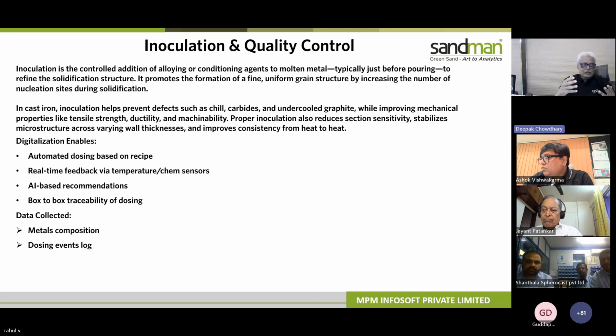I just wanted to draw my thought process with you, Mr. Gadappa. If you have a digital interface like what Rahul showed you, which also has a lot of other data capturing capabilities, and you have all the data on the scrap that you used, all the temperatures that you have used for a particular type of castings, you will be able to do a clear cut root cause analysis of what scrap combination caused you the maximum problem, what gave you the best uniform hardness, and what inoculation gave you the best pearlitic or graphitic structure. These are answers which are lying hidden in the reams of data that is already being generated by you, but is not being captured for action by foundrymen. I hope I make this point very clearly. This is a classic case of having a repeatable situation which can be answered very well within your own data sources. Just a point, Mr. Gudappa.